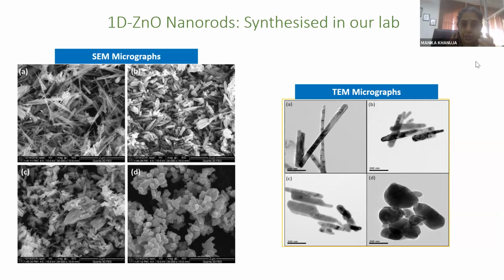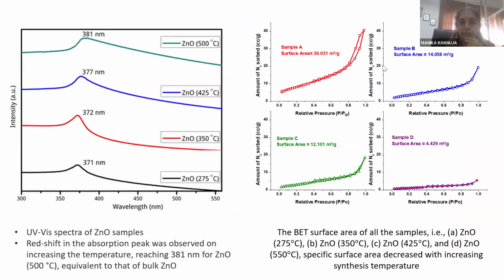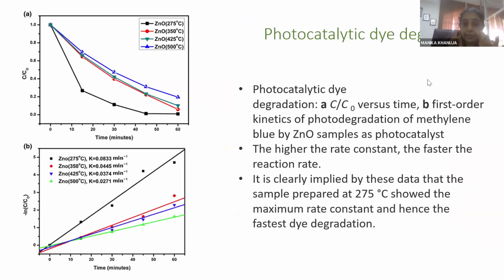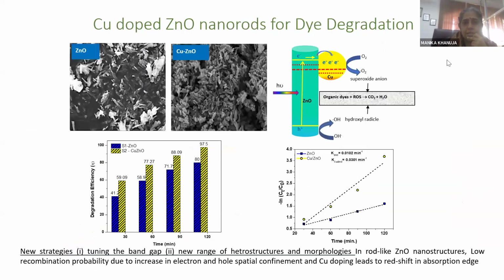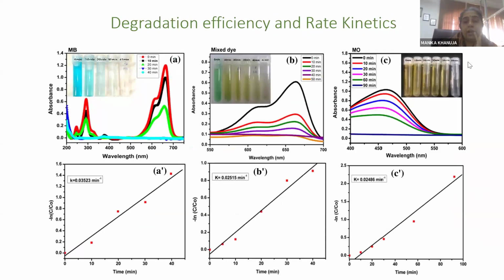We have collaboration with AIMT, and these are zinc oxide nanorods of different aspect ratio, with SEM and TEM micrographs. Once we have different aspect ratios, we have different surface areas, so we did the analysis through BET. The difference in the band gap we did through UV visible absorption spectroscopy, and then the difference in application, the difference in photocatalytic efficiency also. Some micrographs are shown. Further, we have doped it with copper also, and then the efficiency has increased tremendously. It's used for environmental remediation also.